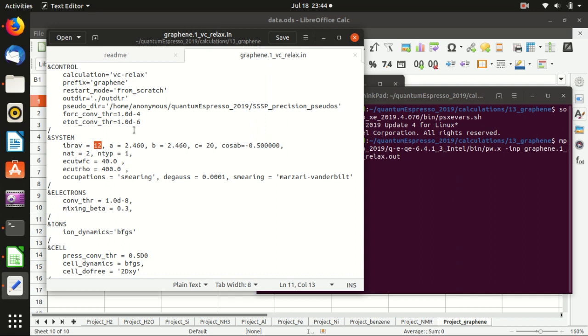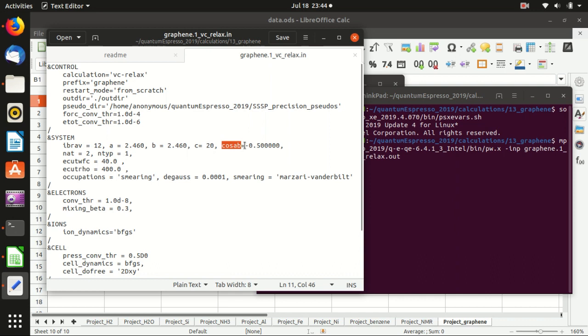We define a, b, c and cosine_ab rather than the cell dimensions 1, 2, 3 that we usually use. Basically a, b, c means the three lattice vectors in units of Angstrom, not Bohr. The a and b lattice vectors are 2.46 Angstrom, and the c lattice vector is 20 Angstrom, which is very large. The angle between the a and b vectors is 120 degrees, so cosine_ab is −0.5.